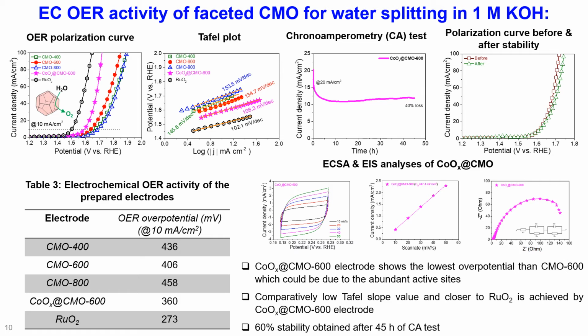of electrolysis. Then the polarization curve also shows that there is some decrement in the activity after the 45 hours of continuous electrolysis. Then the ECSA and the EIS analysis of CoOx coated CMO has been shown here. Here we can see that the higher Cdl value of 47.4 millifarad per centimeter square is obtained for CoOx@CMO 600 electrode, which is due to the more number of active sites provided by this CoOx co-catalyst to CMO 600 electrode.